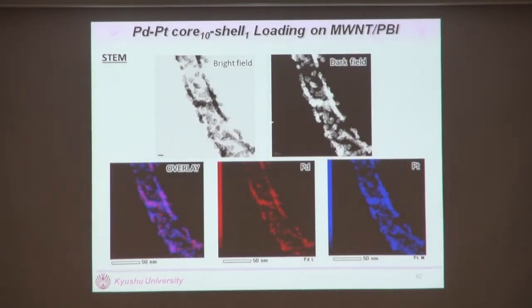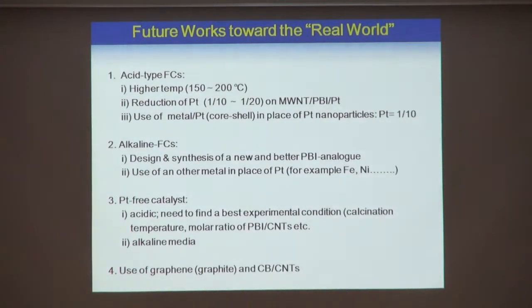And here is palladium platinum core shell. One of the PhD students just succeeded in the preparation of core shell metal like this. And here, the shell is platinum and palladium core, and so this is overlay, and you can see a clear core shell structure. So that result indicates that we can reduce the amount of platinum. Yeah, I should stop. Okay.